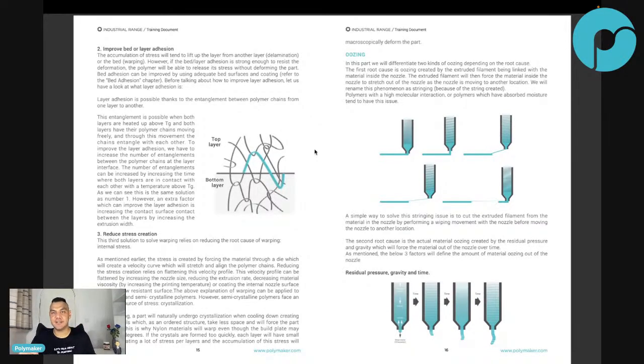When you print with PC, why do you anneal PC? It doesn't even crystallize. Is that because of thermal expansion, thermal shrinkage? No. It's because you stress all the filament during the printing process. So you anneal it to release the stress. The whole part, you are bringing it close to TG, so that all the stress inside is suddenly released. We say anneal PC to have great mechanical properties, but the actual thing is anneal PC to keep the mechanical properties over time.